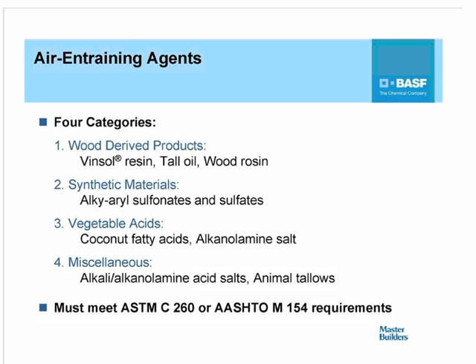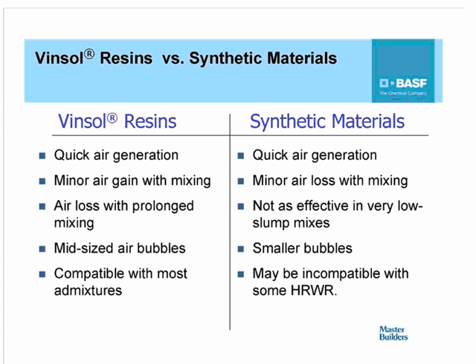Now, there are different types of entraining admixtures in the marketplace, and entrainers, as I indicated at the beginning, are governed by ASTM C260. But the entrainers in the marketplace can basically be classified under the wood-derived products as well as the synthetic materials. Now, both of these have their benefits and slight disadvantages. With the Vinsol resins or the wood-derived products, you get quick air generation, but minor air gain with continued mixing. However, over time, air loss can result with prolonged mixing.